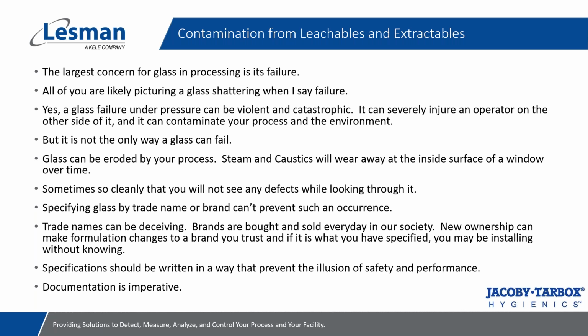In many cases, like with our Unisan windows, they are a glass window that is fused to a metal ring, that ring putting it under compression so that even in an overpressure situation, that glass cannot be blown out. So there are means of protecting from that catastrophic failure. But what about the other kind of failures? These failures are far less common, they're far less talked about, but they are where the source of the leachables and extractables will come from on so many occasions.